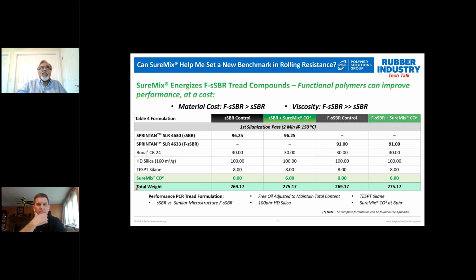So we took two polymers, Sprintan SLR 4630 and 4633, which had very similar microstructure. The main difference is one has functionality and the other doesn't. We also looked at the impact of SureMix in these formulations. So we took our solution SBR control and added 6 parts of SureMix. Here again, we have 100 PHR of HD silica and the recommended 8 PHF, parts per 100 of the filler, of tetrasulfide silane or Si69. Similar approach on the functional polymers: 100 parts of silica, 8 of silane, and then added 6 PHR of SureMix CO squared.